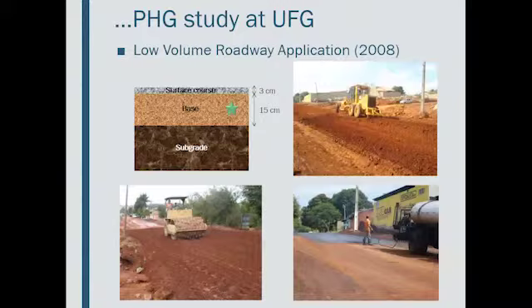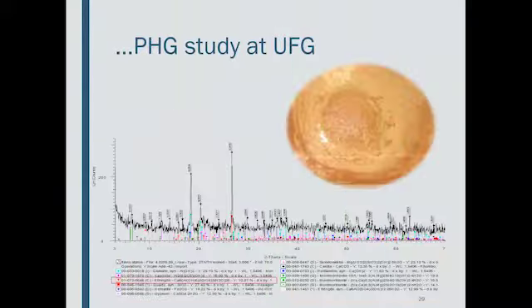Since this construction, we have been monitoring this pavement with field tests. But at that time, we found a problem. When you put this material in contact with water, this thing happened, and we started to figure out why it occurred. Then we performed X-ray diffraction tests and observed the formation of ettringite, a mineral that can cause swelling. And for use as subbase and base materials, you don't want this.